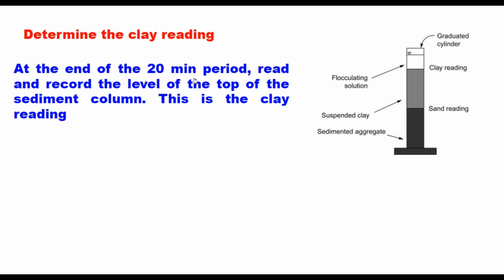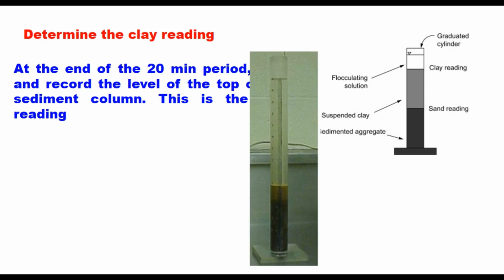So at the end of the 20 minute period, read and record the level of the top of the sediment column, and this is the clay reading. If no clear line of demarcation has formed, allow the sample to stand undisturbed for another 10 minutes and then read the clay reading. If still it is not very clearly visible, then you should repeat the test. This will be the situation: this is the sand and this is the suspended clay layer. So this is to be read as the clay reading.